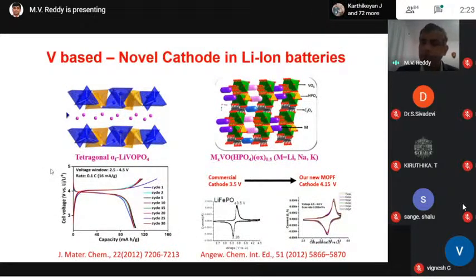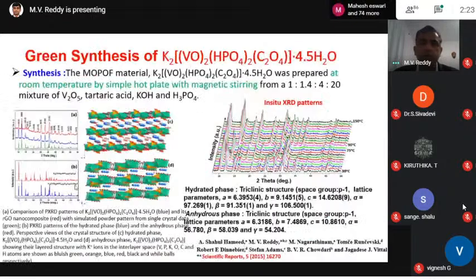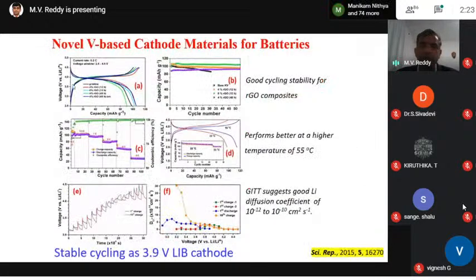The advantage of this material is that we check it in comparison with iron phosphate. Here, 3.5 versus 4.1, in the sense that the higher the redox potential, the better for the applications. Again, we try to use this green synthesis approach. We prepare the materials, and these are the typical charge discharge potentials, almost 4 volts, which is reasonably good when compared to iron phosphate. Still, there is scope to improve the performance further by optimizing synthesis or looking for low molecular weight materials.